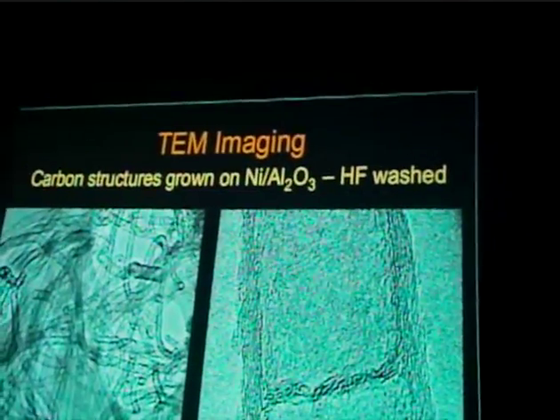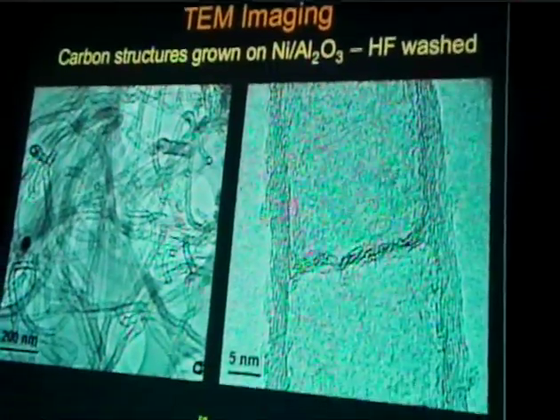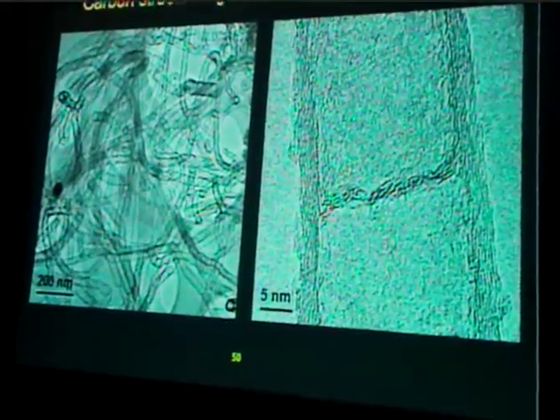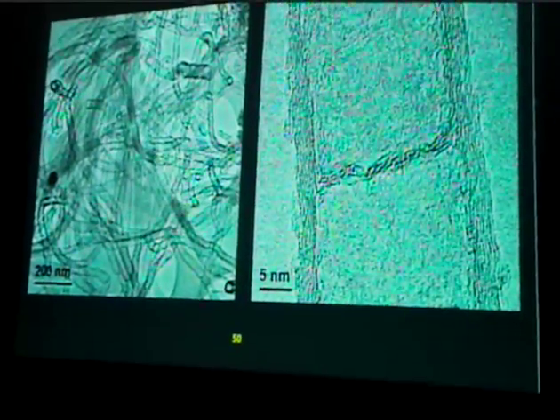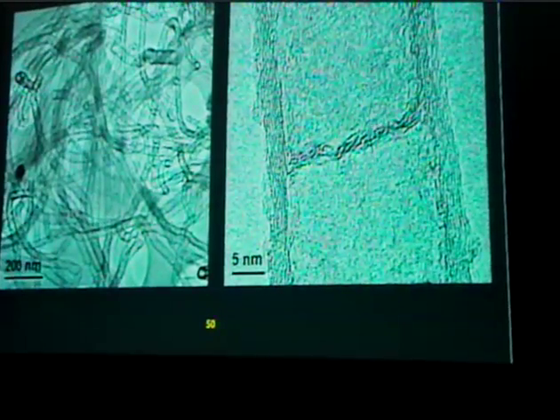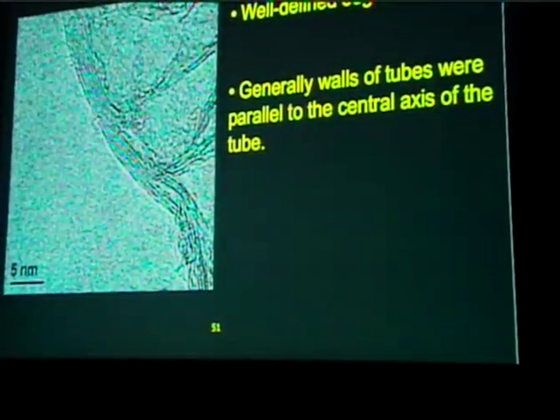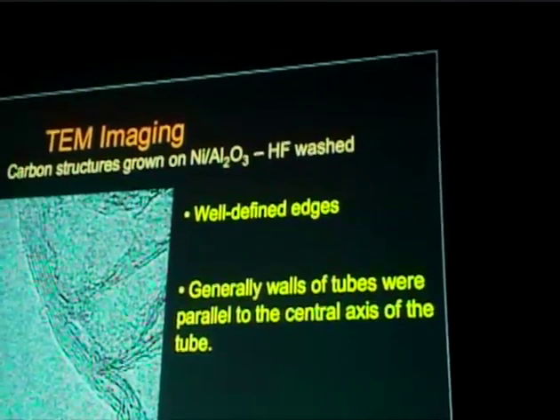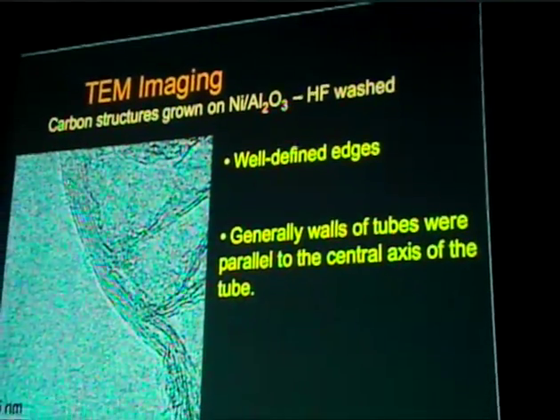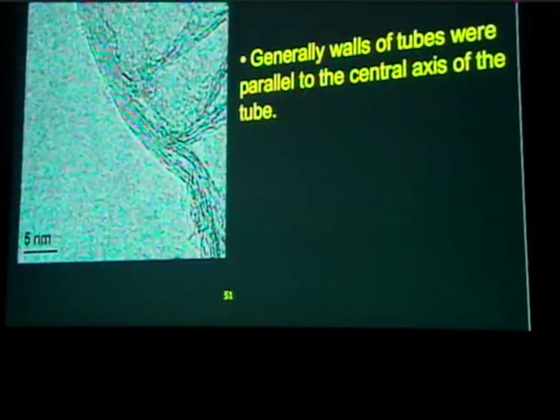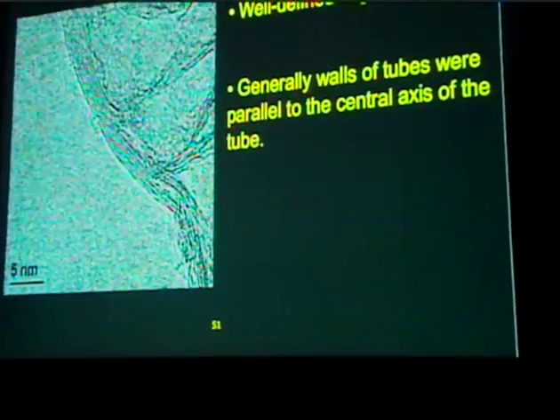You can see multiple carbon, and here are the graphite planes perfectly parallel to the axis of the fiber, so there's essentially no edge plane exposure in these materials. And here's a close-up view of the same catalyst. You can clearly see the basal plane lining up here.